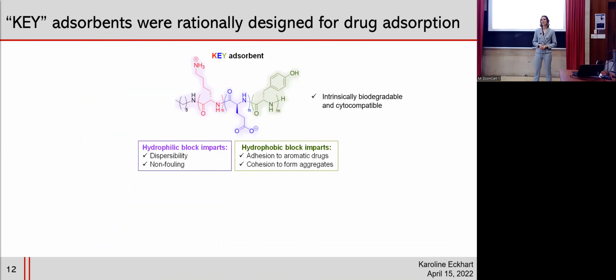So we designed a class of peptide amphiphile adsorbents, which we call keys, and they feature a hydrophilic block made up of lysine and glutamic acid. So the lysine is the K, glutamic acid is the E, and this hydrophilic block affords both dispersibility to the key adsorbent and also it's non-fouling because of the high charge density. The hydrophobic block is made up of polytyrosine, which is represented by Y. And tyrosine features this aromatic side chain, which is both adhesive to aromatic drugs and also cohesive to other key molecules. So it can form discrete aggregates of the key adsorbent, which can adsorb the drug and then sequester it away. And because this material is based on a polypeptide, it's intrinsically degradable and cytocompatible.